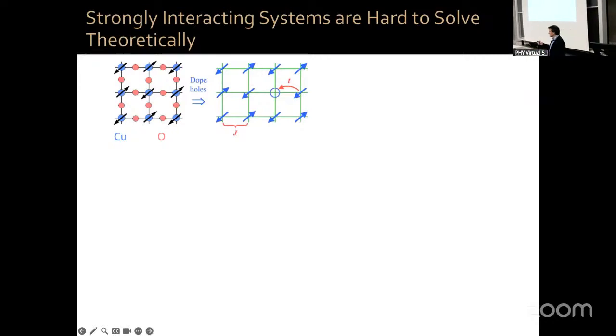However, what happens in this material is that there is a very strong repulsion between electrons, so that double occupancy of a copper atom by 2 electrons is heavily penalized. And as a result, when you grow this stoichiometric compound, you form something known as a correlated Mott insulator, where the electrons get stuck in their positions, and they cannot jump from atom to atom because of a strong Coulomb repulsion between the electrons.